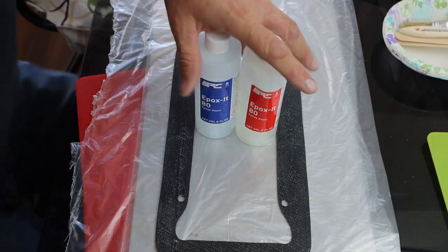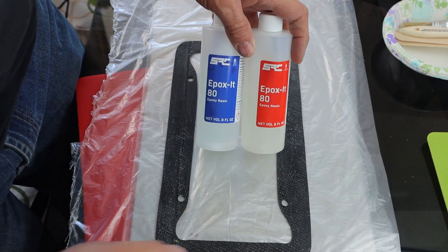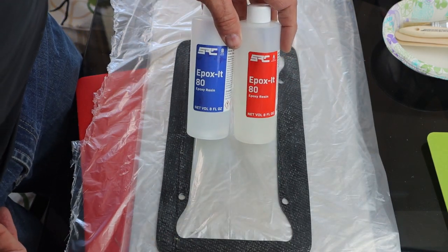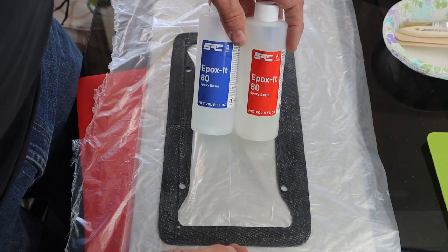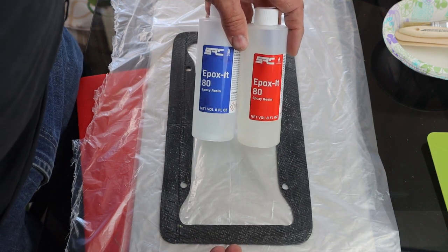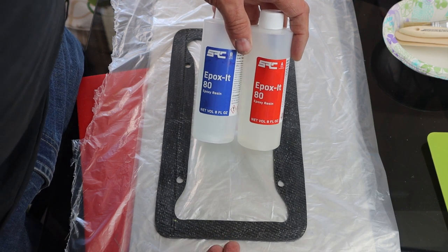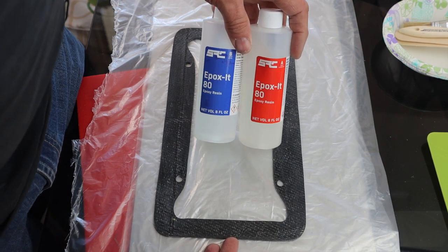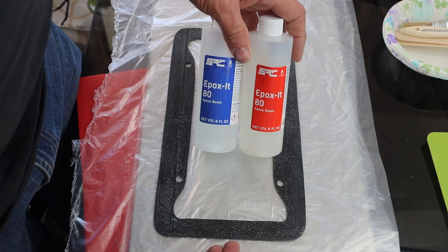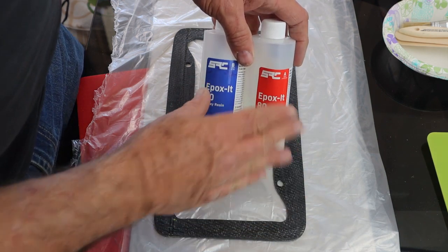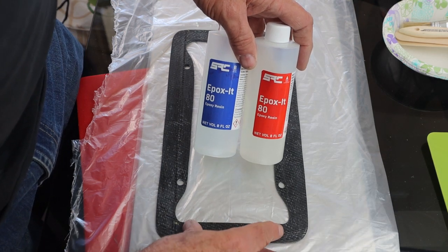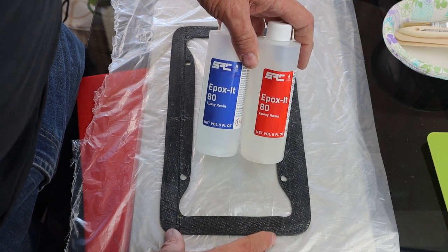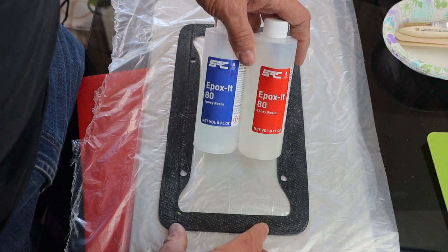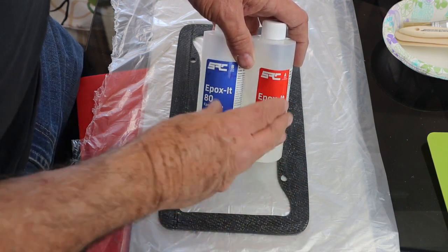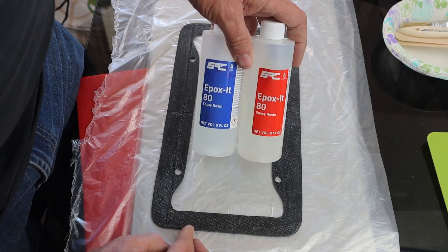Now, one of the reasons we're using the resin system that we are is this resin is a general purpose resin. It's not only good for laminating, but it's also good for casting or surface resin like tabletop resin. This resin has a UV additive to it, which is really good. Carbon, after a while sitting in the sun, will start to chalk out and get really crusty. So one of the reasons why we use this resin is for the UV additive.